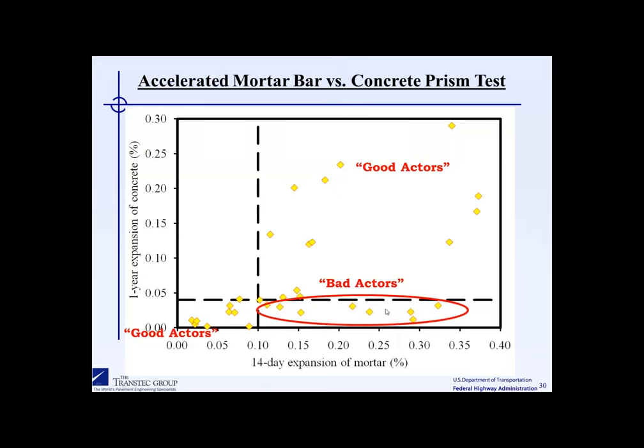Unfortunately, as I showed in the previous slides, we will often find aggregates with quite a bit of data in this bottom right-hand quadrant. I first must mention the axes are reversed from the previous slide, so I don't want to confuse anyone with that. The data shown here will be considered to be the bad actors. These are the ones that are failing the mortar bar test considerably, but they are passing the concrete prism test.